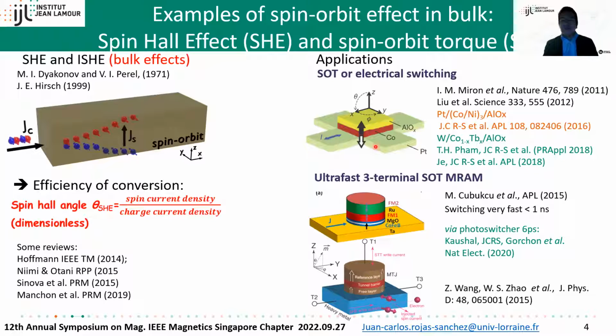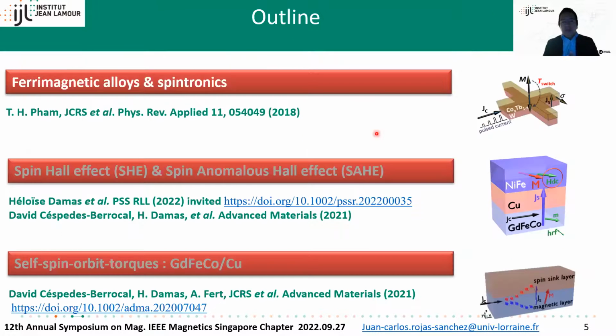Still, we need a small in-plane field to break the symmetry. That's one challenge: to overcome this small in-plane external magnetic field that we need. The other is to look for materials with a larger spin-charge current conversion efficiency. And I will show you that magnetic materials with strong spin-orbit coupling could also be good spin current emitters, and we can even talk about self-torque in the magnetic material. But before going to this point, let me first recall what a ferrimagnetic rare earth transition metal alloy is.